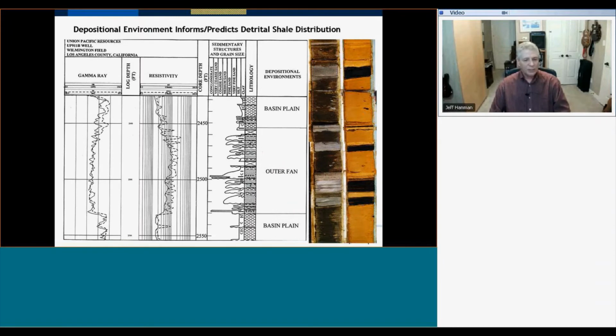Okay, so as an example of the geological information, we see a log, we see that it is layered, and it's fairly close to the resolution of the resistivity log. We see an expression on the gamma ray. We see an interpretation of environment. In this particular case, we're looking at a turbidite. Turbidites often, particularly on the fringes, will have some thin beds, and that's what we see in a white light core photograph and an ultraviolet light core photograph. The gray is the shale, or in this case, the black in the ultraviolet is the shale. The sand here is actually a lighter gray. You can see some invasion, and the darker parts are due to oil staining, and so the whole thing fluoresces.